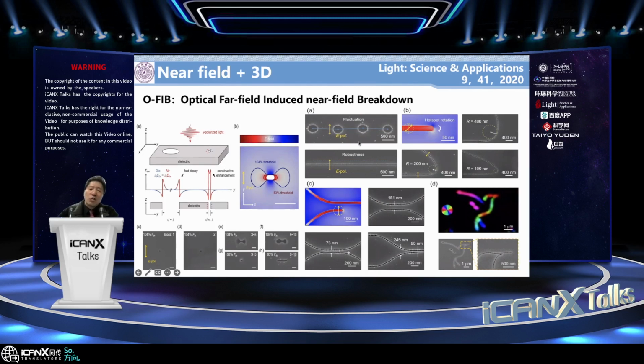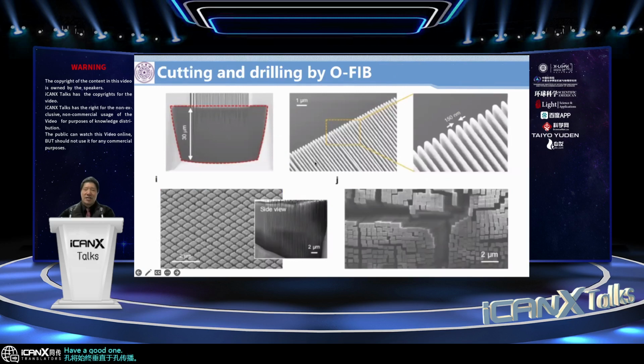If we change the polarization, then the hole will always propagate perpendicular to this. I will give you the example. Here we use this OFIB effect to do very deep cutting. In this case, we have the material, a sapphire sheet. The width of the single sheet is only 150 nanometers, very narrow.